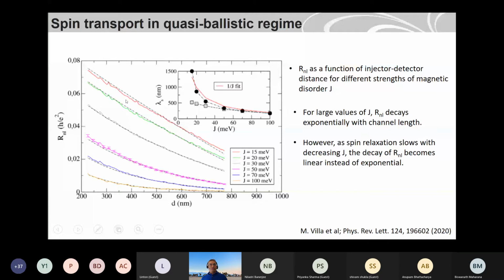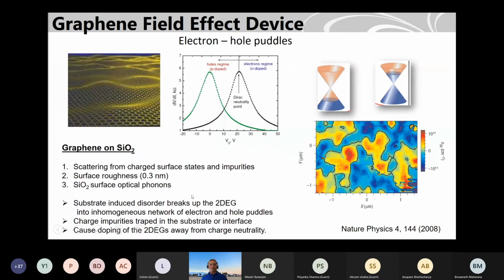And continuing with this calculation, as you see here, if there's less magnetic impurity, so this J is very small, around 15 here, then the spin signal, this is the spin signal with distance, is actually going linearly. But if you have a higher order of magnetic disorder, it's exponential. So that is the summary of the paper.